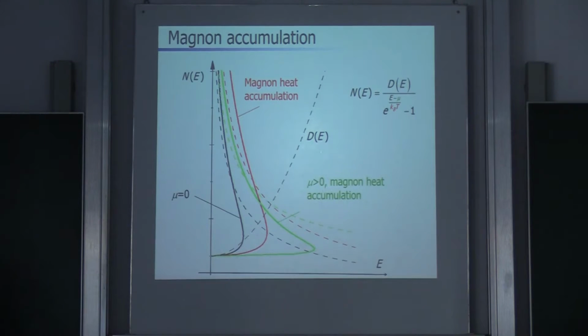function. Now, actually, there is no microscopic reason why it should look like that. It's just a way to parameterize the distribution function and to allow something which looks like a quasi-equilibrium state. So the situation is quite similar to the one of the spin accumulation in metals. We do not really know that we can describe them by a Fermi-Dirac distribution function with a certain temperature, but we can parameterize it this way.